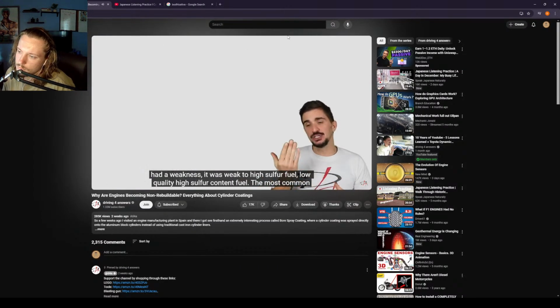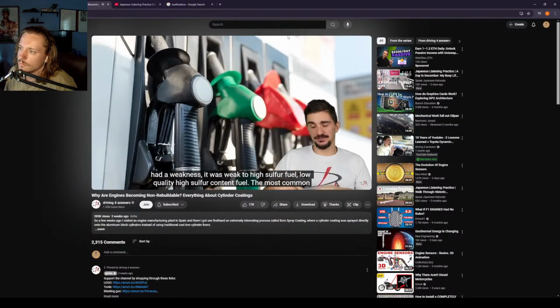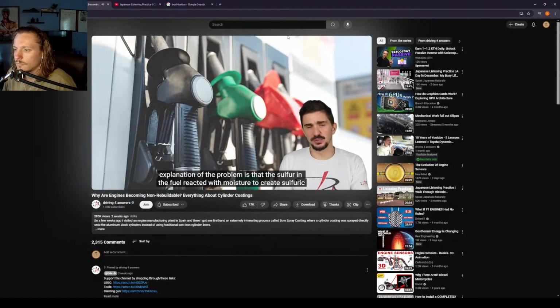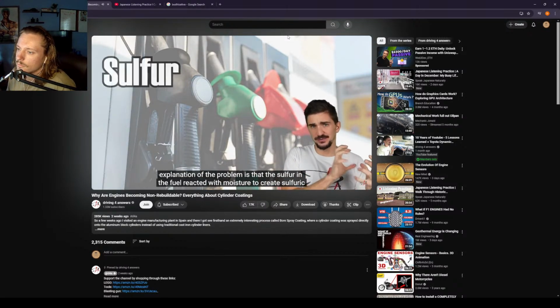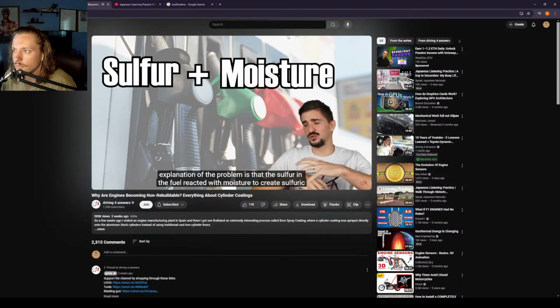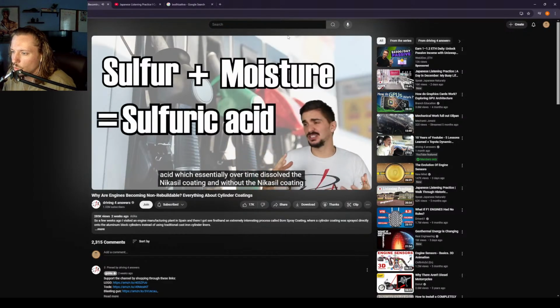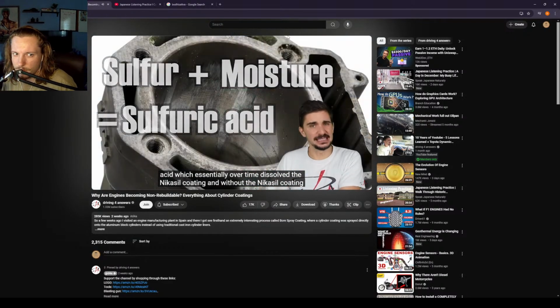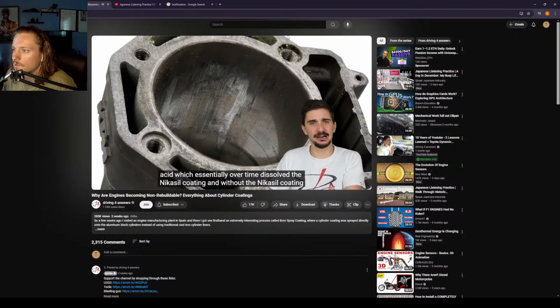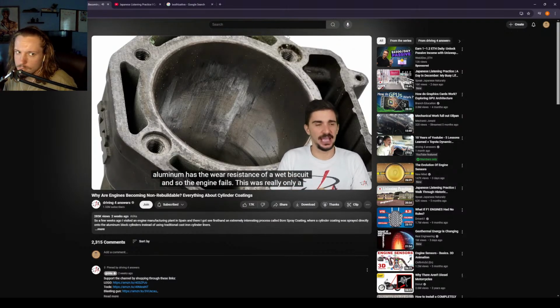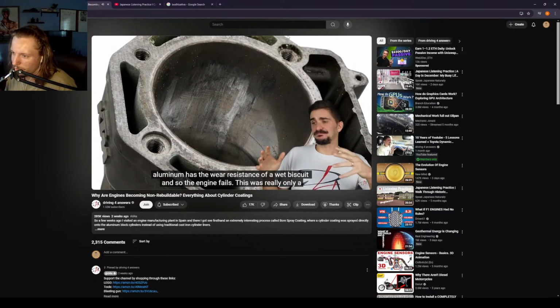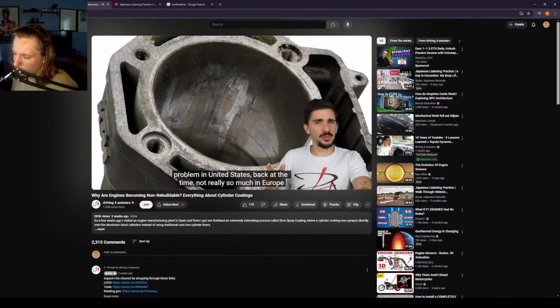It was weak to high sulfur fuel, low quality, high sulfur content fuel. The most common explanation of the problem is that the sulfur in the fuel reacted with moisture to create sulfuric acid, which essentially over time dissolved the Nikasil coating. And without the Nikasil coating, aluminum has the wear resistance of a wet biscuit, and so the engine fails.